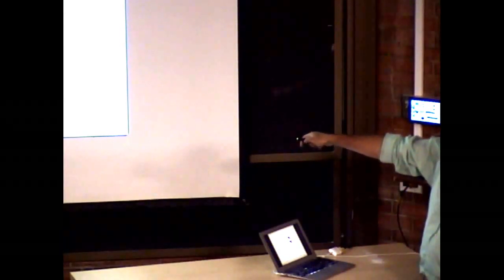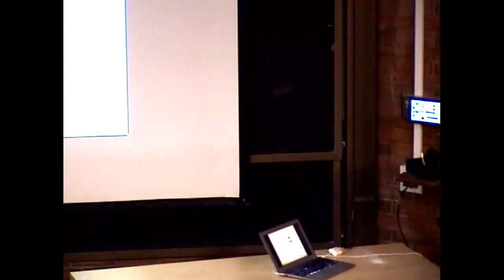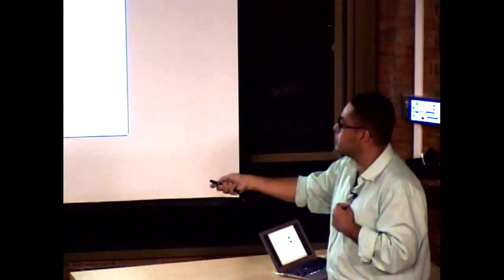Here's a photoluminescence spectrum at low temperature. So here we have a very weakly allowed 0-0 vibronic origin. This is a 0-1 feature, 0-2, and so on. And there's a very well defined intensity distribution that tells you to what extent the molecule needs to reorganize in the excited state to relax the new electronic distribution once you excite. And so this is a typical vibronic progression. This emission should have been completely suppressed, but it's a little bit allowed. And it's allowed due to energetic disorder, and you can actually analyze this relative 0-0 intensity to learn something about the nature of the disorder, which is a detail that I won't get into because of time.